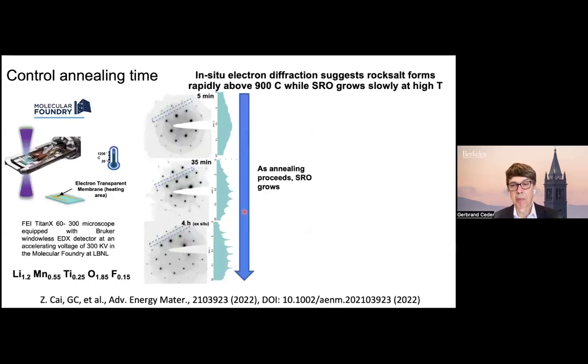But by far, the most practical way to actually control the short-range order is to control the heating and cooling profile. So what we have learned in DRX is to actually control the annealing time. You really want to minimize the time spent at high temperature, because what I'm showing here, this is in situ electron microscopy that was done by my colleagues at NCEM. After 5 minutes above 900 Celsius for this specific composition, the rock salt has formed, but there's no short-range order.